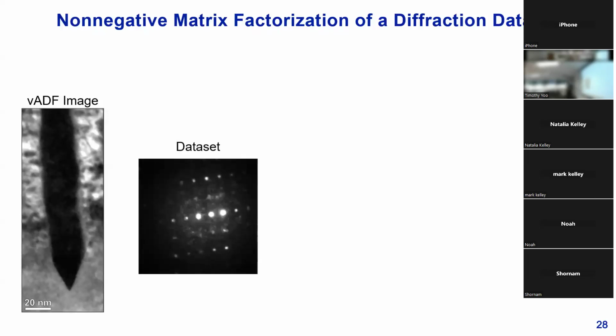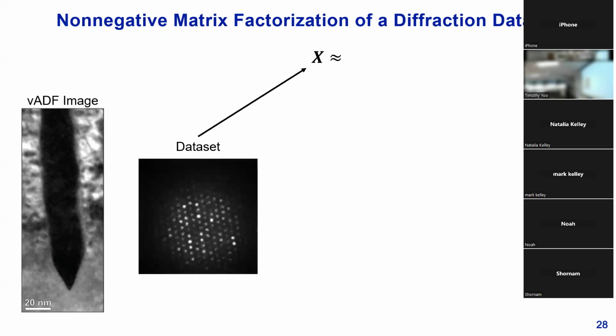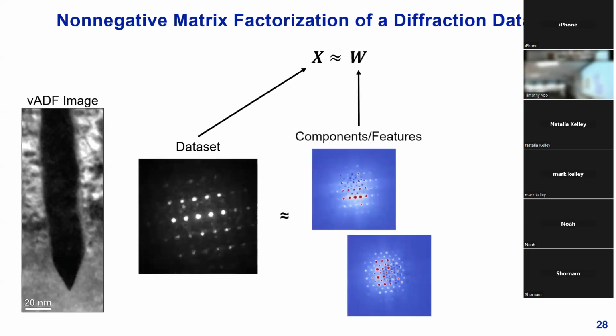We take our 4D-STEM data set as being portrayed by this nice video here, and we're going to call this input data set our matrix X. And so what this is going to be doing is that our matrix X is going to be approximated by a product of 2 other matrices. One of them is going to be components, features of the data set. These features might even resemble diffraction patterns themselves, although they're not necessarily any of the data, as well as the corresponding weights or coefficients of how strongly does each feature correspond to your original data.